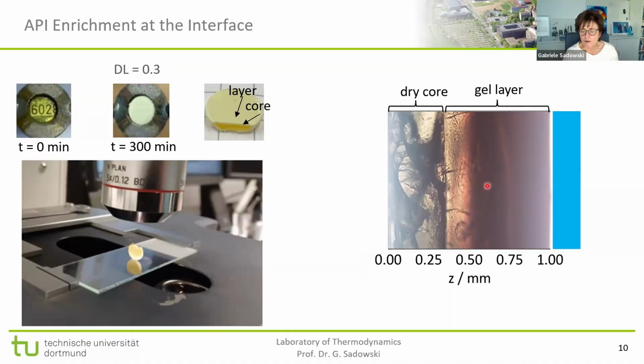Whereas the two molecules, polymer and API, are diffusing from the left to the right. And what you see here is that at the outer part of the ASD, we really have what we call the gel layer. This is where the water already moved into the tablet. And then we have the dry core, which the water didn't reach so far, and they look quite different.